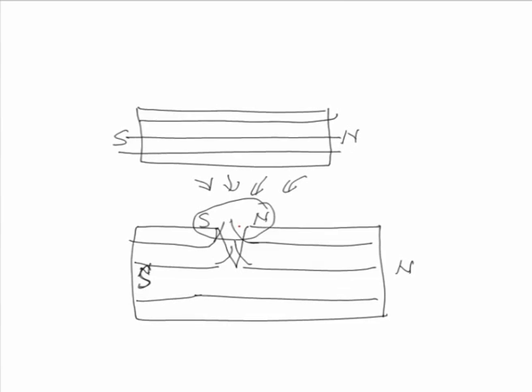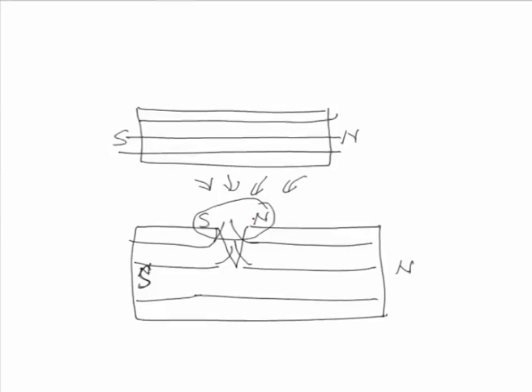So, if the defect is very clear, then powders will tend to segregate in the areas where the defect is present, because the leaking magnetic field will attract the powder particles and segregate them in a particular pattern. So, wherever the defect is present, say this is the line along which the defect is present, then powder particles will tend to cluster and segregate around it.